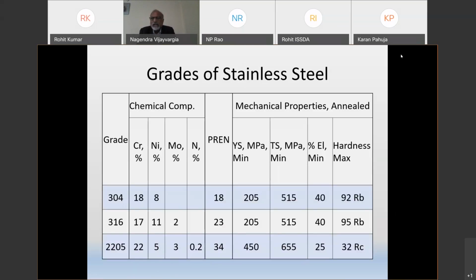I would like to cover only 2-3 grades which are important for this. There are 3 grades which are important: 304, 316, and 2205. 304 and 316 are both called austenitic stainless steel, and 2205 is called duplex stainless steel. You can see the chemical composition in these, but the most important thing is PREN, the pitting resistance equivalent number.